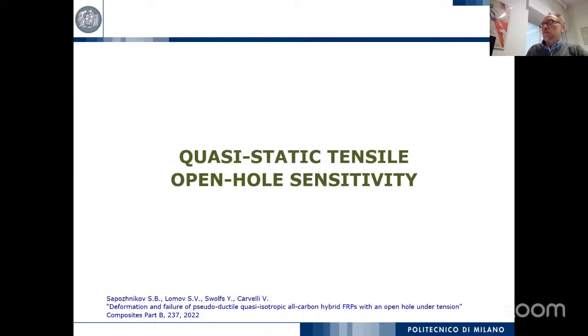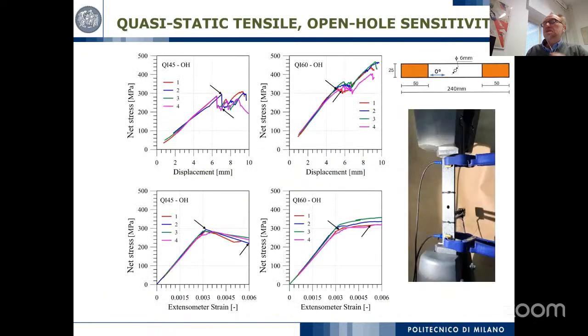Then moving to the behavior in terms of notch sensitivity, this is quite standard too, the same setup, same measurement technique. In this case, we limit our test to the two quasi-isotropic laminates, and then you see here only the beginning of the plateau, so when this starts, the first fragmentation, and then the beginning of the plateau in terms of pseudo-ductility.